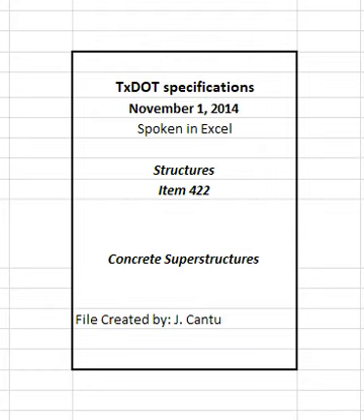Bonding agents are not required unless indicated otherwise. Coat the joint surface with bonding mortar, grout, epoxy, or other material as indicated on the plans or other items if a bonding agent is required. Provide Type 5 epoxy per DMS 6100, Epoxies and Adhesives, for bonding fresh concrete to hardened concrete. Place the bonding epoxy on a clean, dry surface, and place the fresh concrete while the epoxy is still tacky. Place bonding mortar or grout on a surface that is SSD, and place the concrete before the bonding mortar or grout dries. Place other bonding agents in accordance with the manufacturer's recommendations.